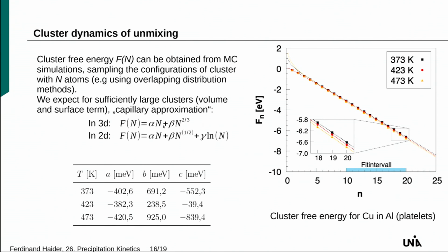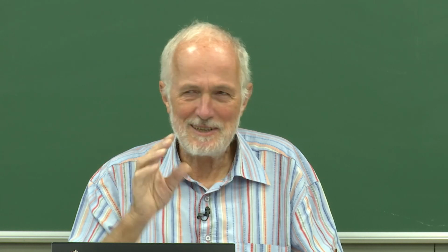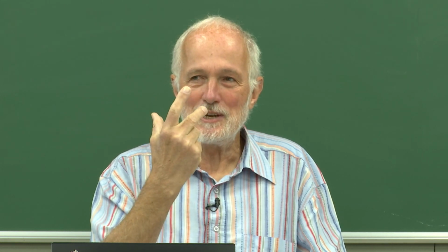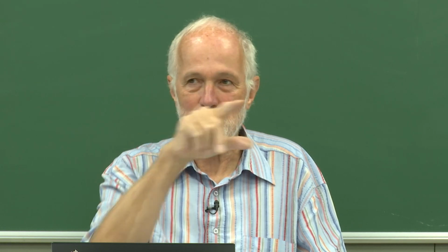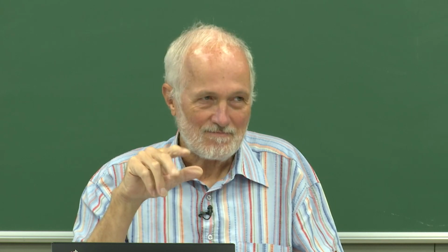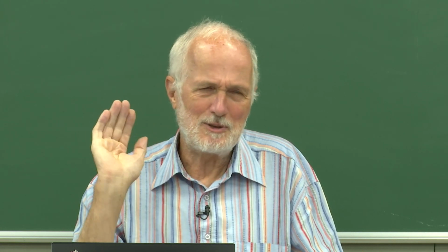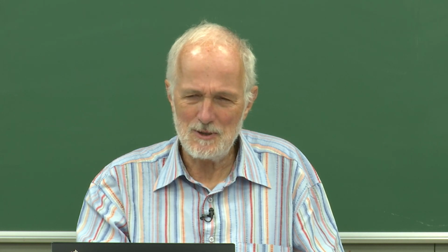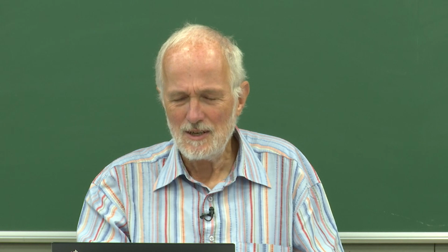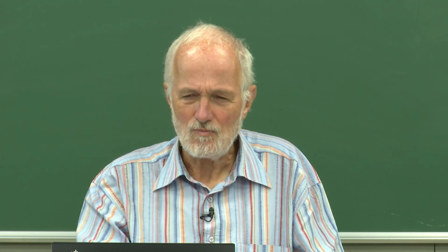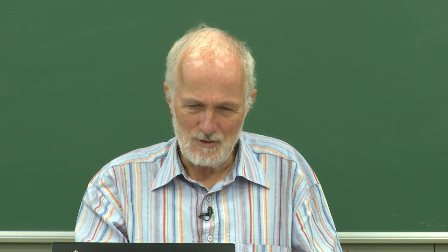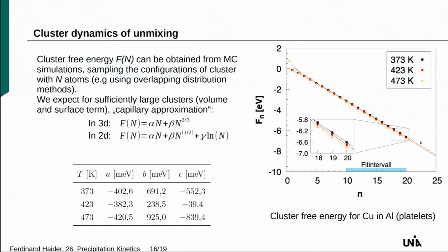Here for this case, you can do the calculation of the configurational sum up to cluster size 3 or 4. I forgot, I once went through this exercise. For 3 it's simple. If you have next neighbor interactions, you have a linear and you have a triangular, and no, an FCC. So that one can, but for 4, I think it's already becoming tedious. Here in 2D, I think you managed to calculate it on paper up to size 6 or so. And the rest of the points comes here from these Monte Carlo simulations. And this is fitted by this function here. That's the function which is plotted here with a dashed line.